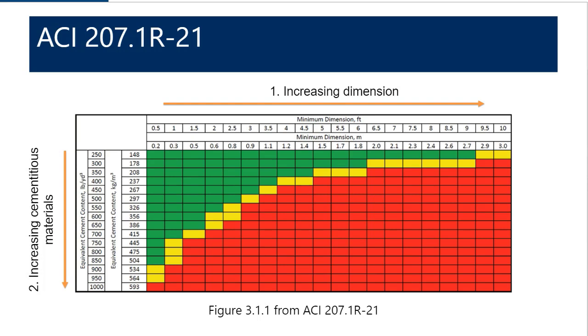What you can see is that you can have an element that's, say, 6 feet thick, but only has 300 pounds of equivalent cement content, and that might not require a thermal control plan even though it's 6 feet thick. However, you can also have an element that's 2 feet thick that has 1,000 pounds of cementitious material. And even though that's only 2 feet thick, that's considered mass concrete because it's this class of thermally controlled concrete. And we've actually encountered situations where we've had 2-foot thick elements that we've had to write thermal control plans for because the concrete had so much cement in it.